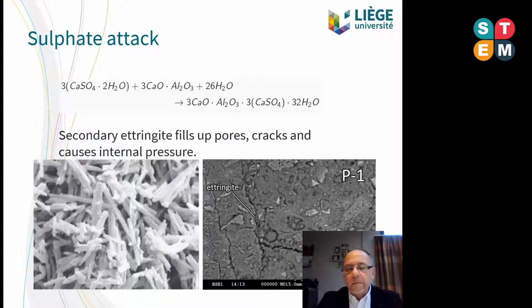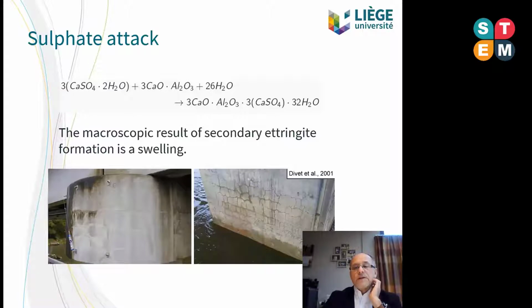by this internal pressure can induce very, very big deterioration of the concrete. That's why there is a big and a strong limitation of the use of this material. The consequences at the structural level is this type of degradation with a lot of cracks, crocodile skin pattern cracks, which is induced by these internal pressure, specifically in structures which are in contact with the water.